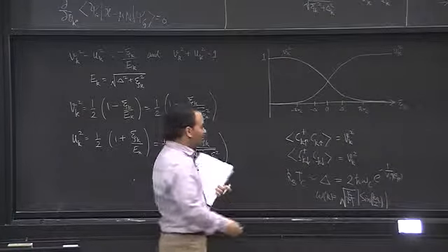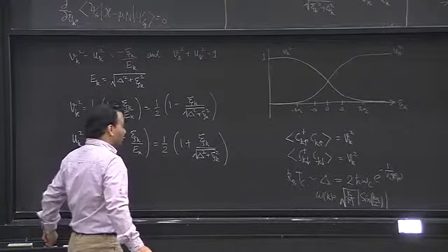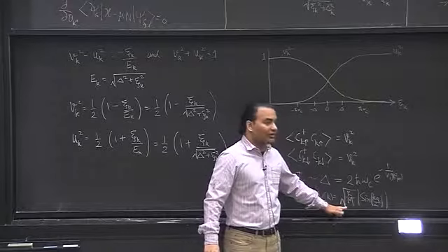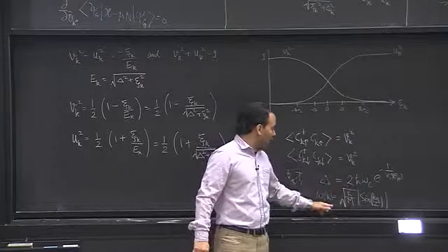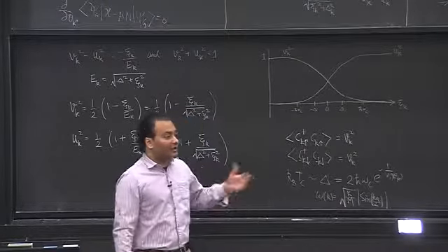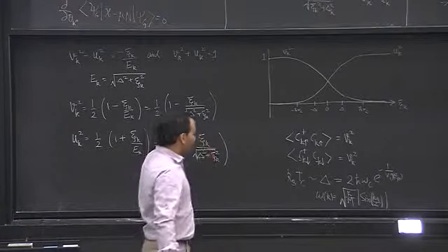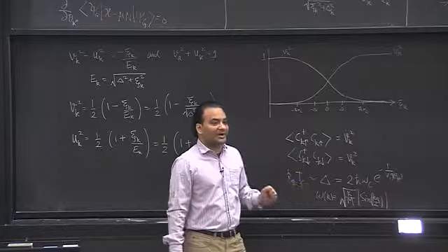So this is the dispersion relation of phonons. That means this energy scale omega_c really goes as 1 over square root of capital M. That means T_c goes as 1 over square root of capital M. And this was one of the things that we knew experimentally, the isotope effect for the superconductors. So this theory can explain the isotope effect measured by experiments.